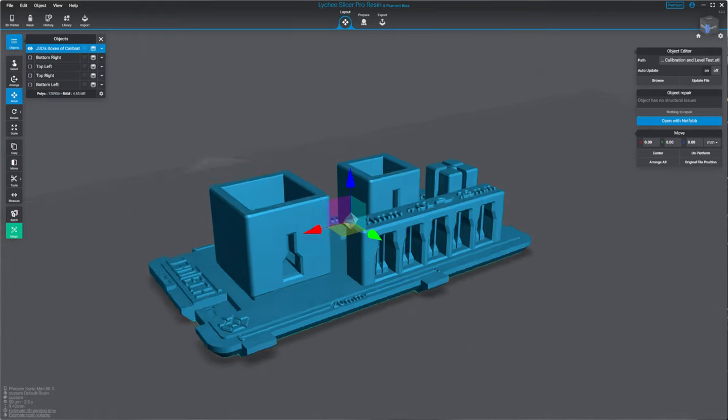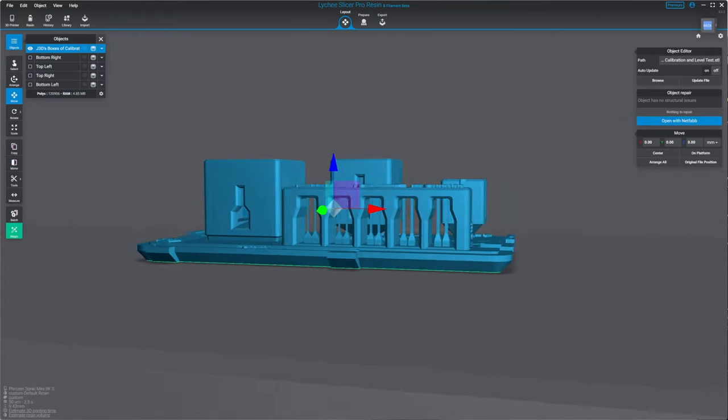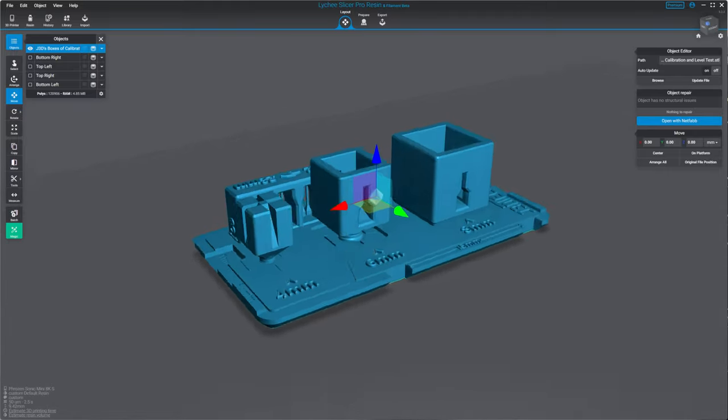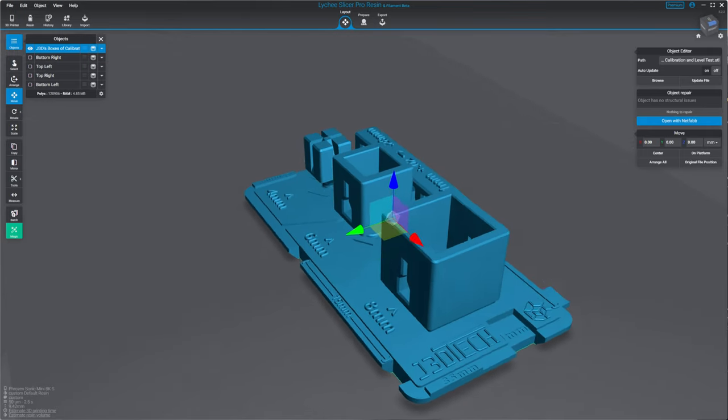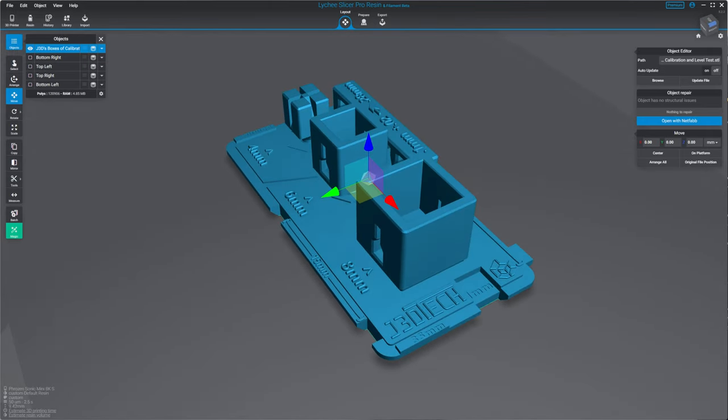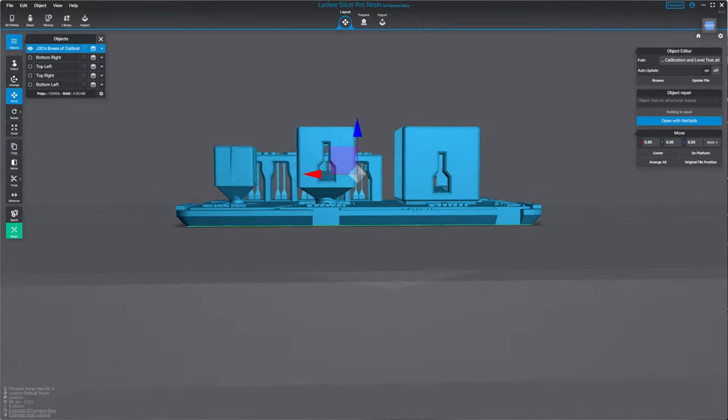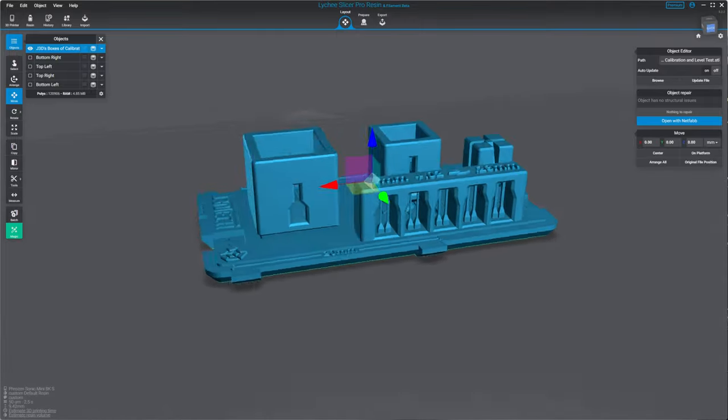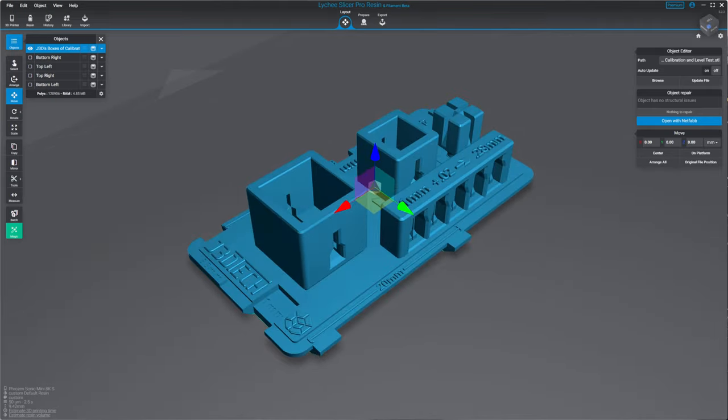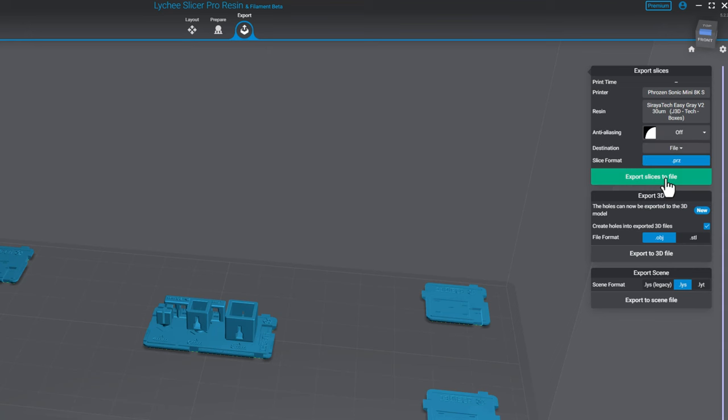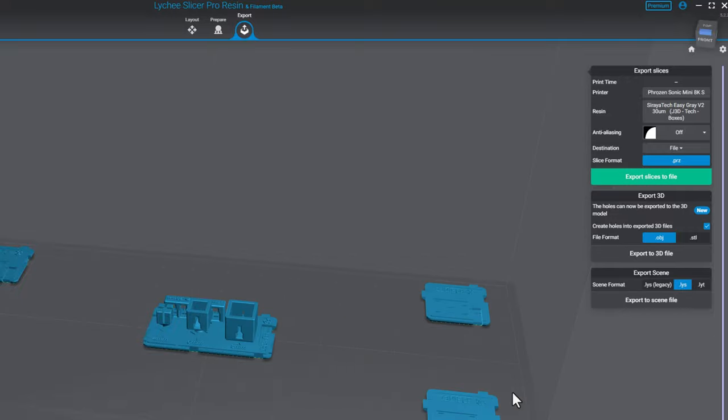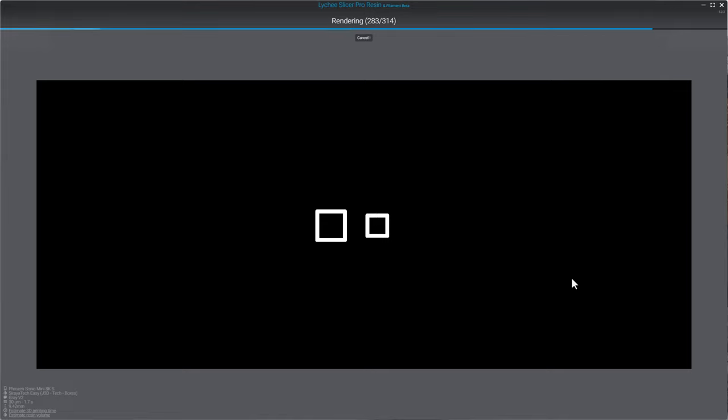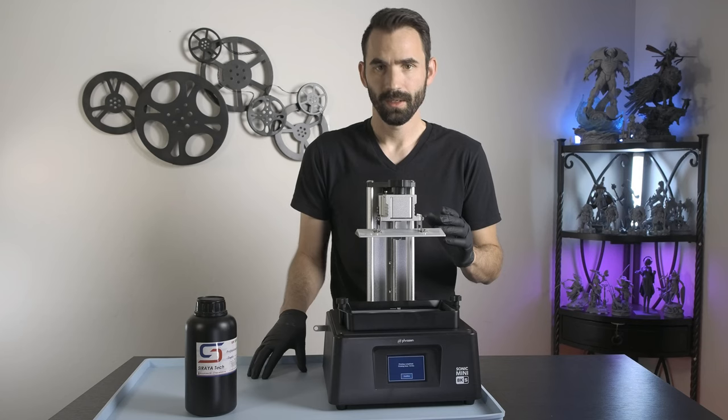Now if resin tensile strength is more what you're after and not dimensional accuracy, you can also just keep increasing your exposure until all the pillars print, ignoring whether or not the boxes fit or not or how they measure. This will give you a resin tensile strength type calibration, which can be really useful if you're printing pre-supported models that are a little bit under-supported. You want to make sure anti-aliasing is disabled when doing calibration prints as it can interfere. Next, click export slice to file. You want to make sure you're saving it directly to your hard drive and not directly to your USB. This is because if you save it directly to your USB, you can increase the chance of failure through data corruption.